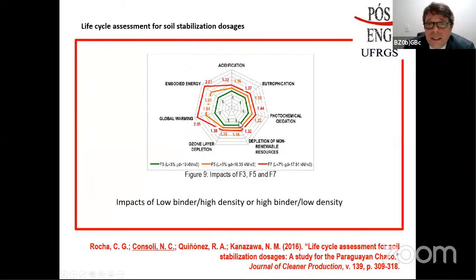Just to finish, we show also that regarding life cycle analysis and sustainability, we can see that if you do a mix in which you could get a unique result of strength, on one side, using the smaller amount of lime, for example, and the densest way to get the result, or something that is not compacted too much but adding a higher amount of lime. In terms of sustainability, the one that uses a higher amount of lime and not so much energy has problems regarding embodied energy and global warming. So we show in the end that if you can choose between adding more lime or compacting more, in terms of sustainability it is always better to use smaller amounts of lime and compact more. That was published at Journal of Cleaner Production in 2016.